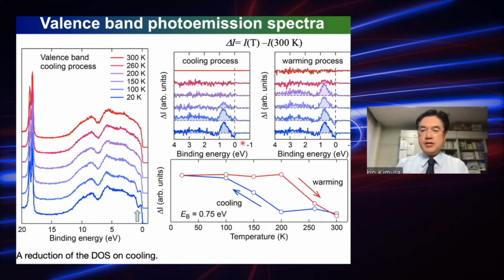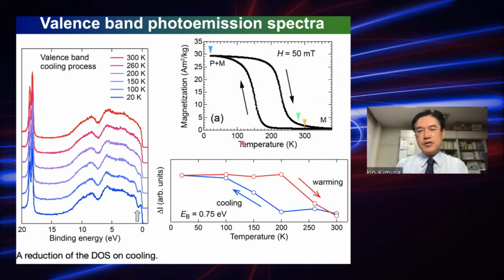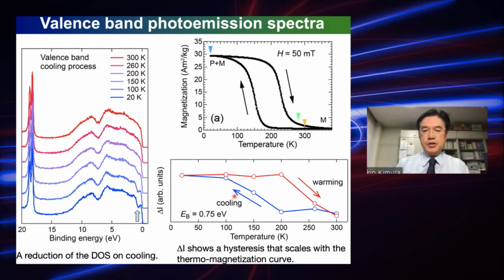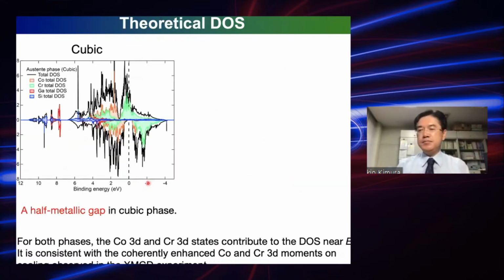Actually, this change scales exactly with the magnetization curve, so that indicates this density of states change is due to the martensitic phase transition. So I believe that the electronic state near the Fermi energy is again responsible for the reentrant martensitic phase transition.